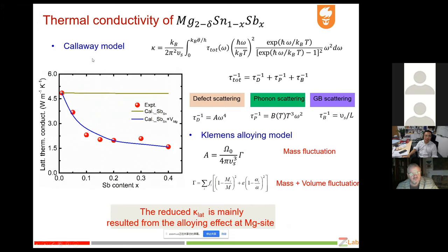So by considering the Callaway model, we can fit the lattice thermal conductivity as a function of the antimony content, and also we need to consider the contribution of the magnesium vacancy. Generally, we can see that the appearance of magnesium vacancies significantly reduces the lattice thermal conductivity. That can be considered as the alloying effect.